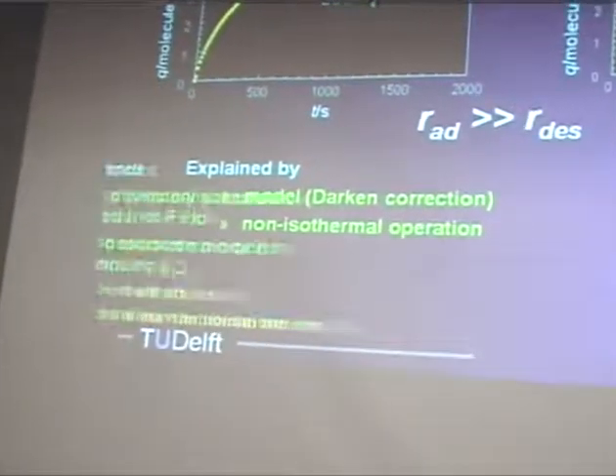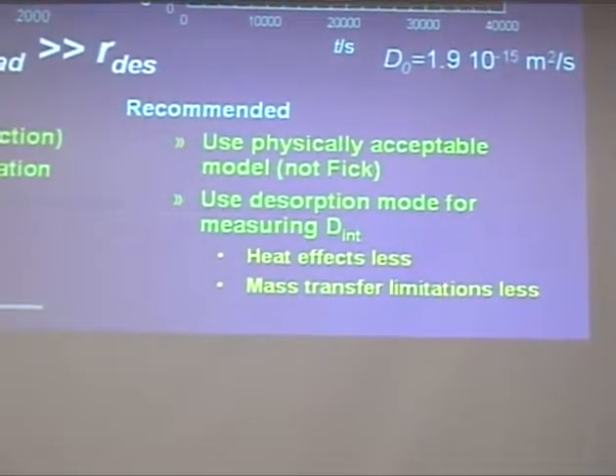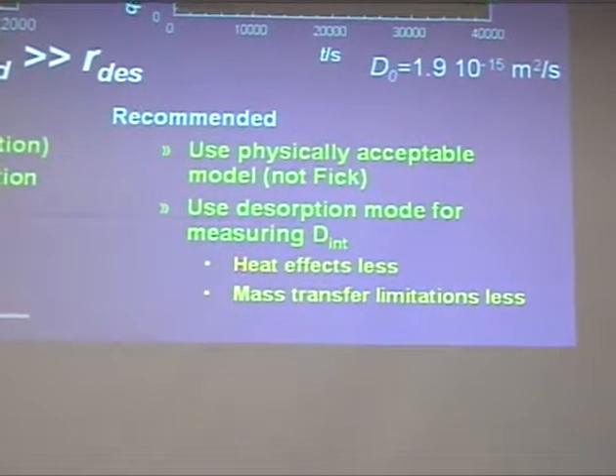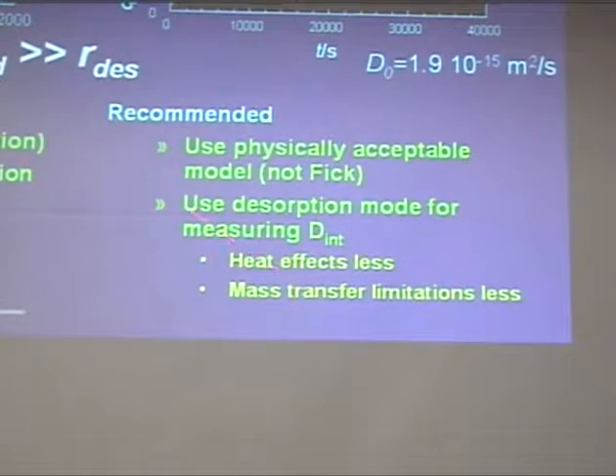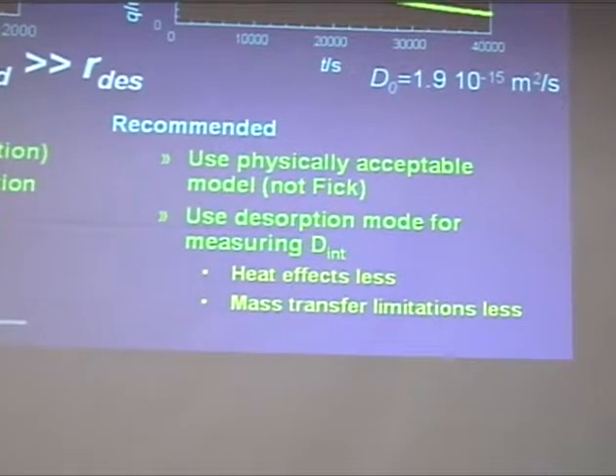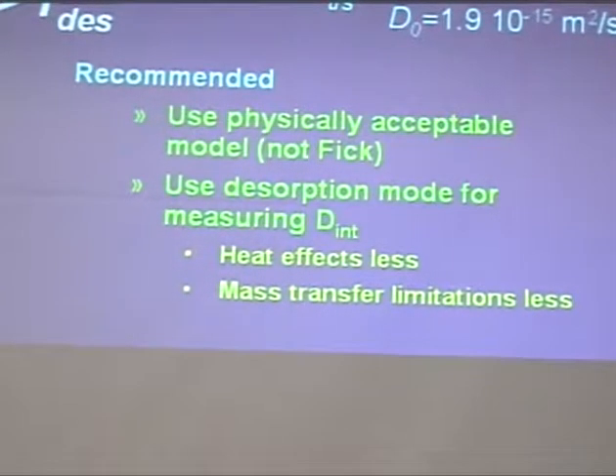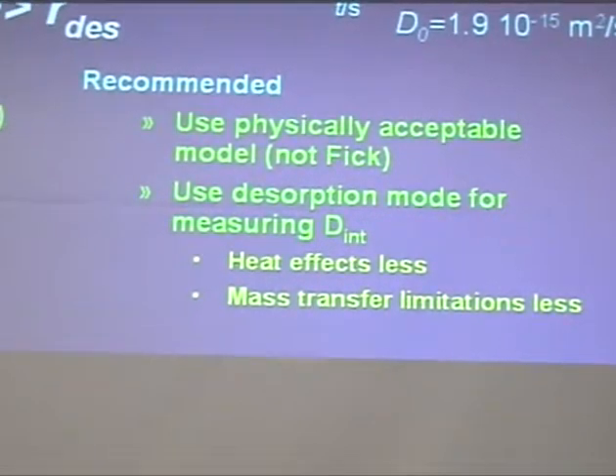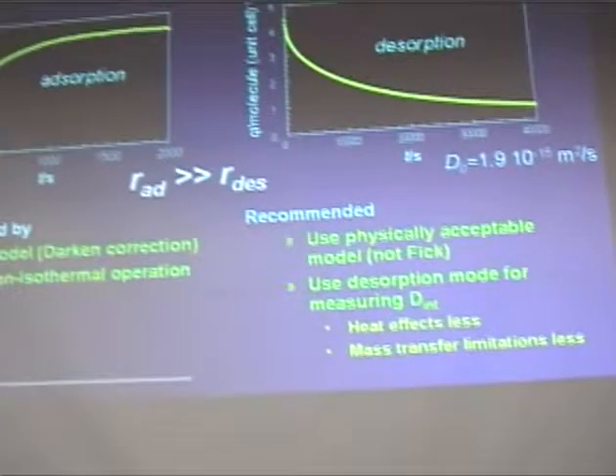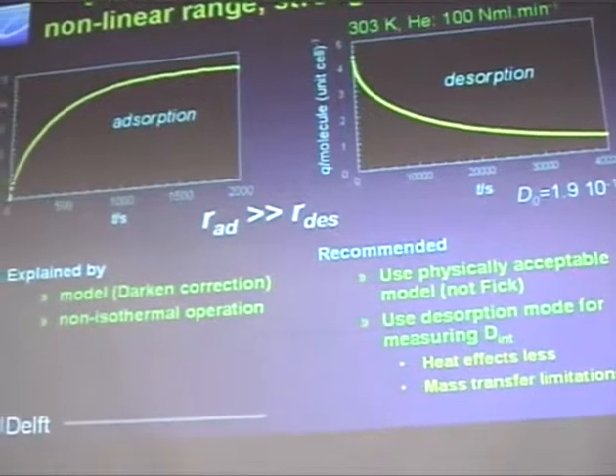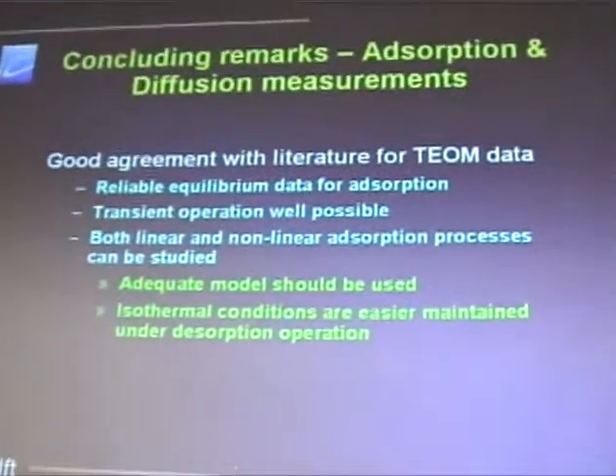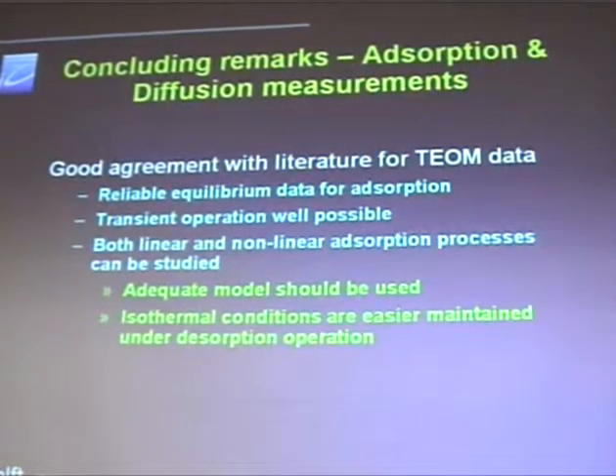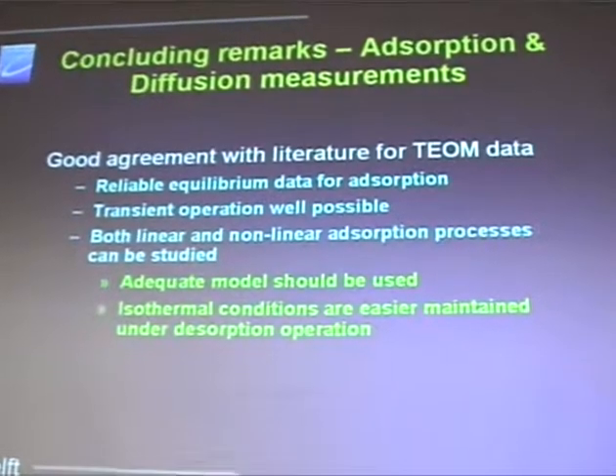Again, the explanation is the model, and the recommendation is not to use Fick, but we know that, of course. The TEOM gives very good data for two reasons: heat effects are less, and you have much less mass transfer limitations, which of course matter. So the conclusion is that you can use the TEOM very well.